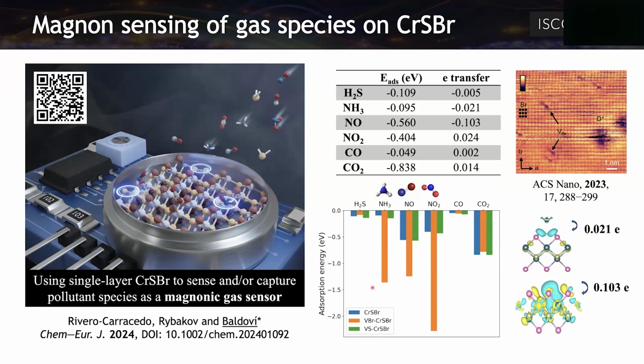The effect is not as drastic, and when we have these vacancies of bromide, that are the most likely to occur in this material. So it's a good material to capture this kind of gas molecules.